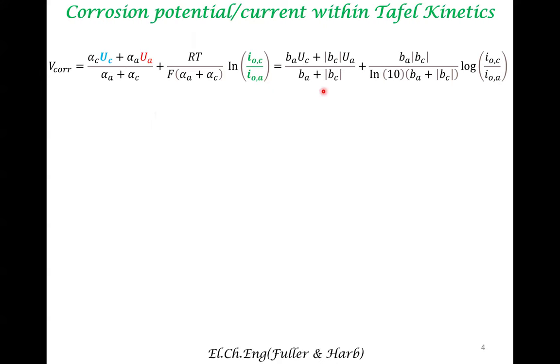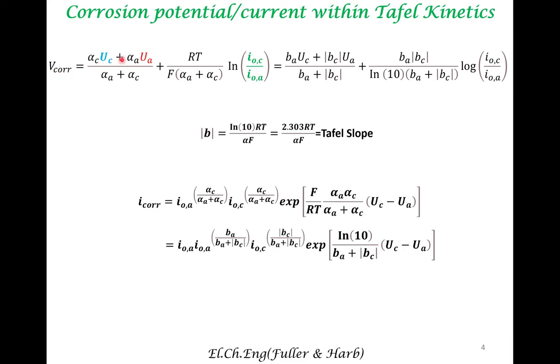And this formula is related to Tafel slopes. The Tafel slope has been defined in previous lectures. So once you know the Tafel slope corresponding to the anodic reaction and the cathodic reaction, and UC and UA corresponding to cathodic equilibrium potential and anodic equilibrium potential, and the exchange current densities, you can plug these things in to get the corrosion potential. You can rearrange these quantities in terms of this formula.